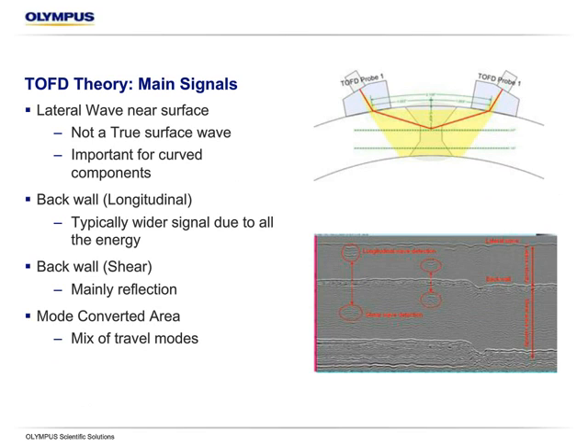So a little bit deeper look at the main signals. So again, the lateral wave is a very near surface wave that travels directly across. It is not a surface wave or a creeping wave. If you're familiar with those terminologies, if we had a cap on the top of this weld, it would not actually follow the contour of the cap or any other geometry in our part. It needs a certain amount of volume of material to actually exist and propagate.